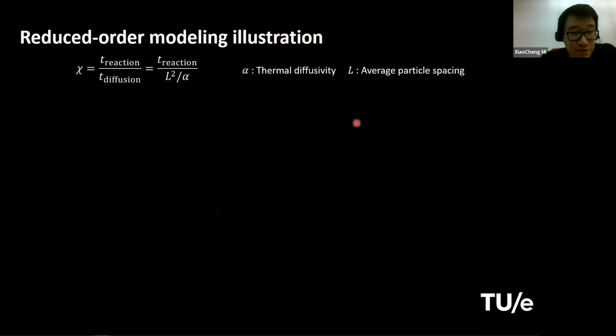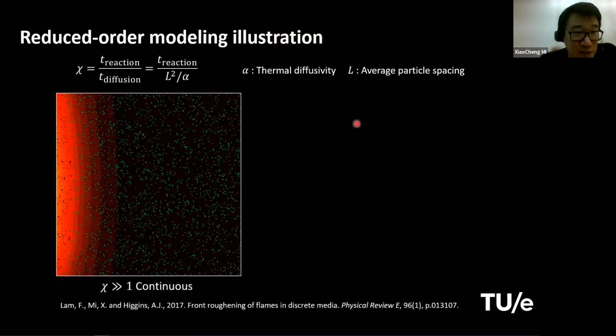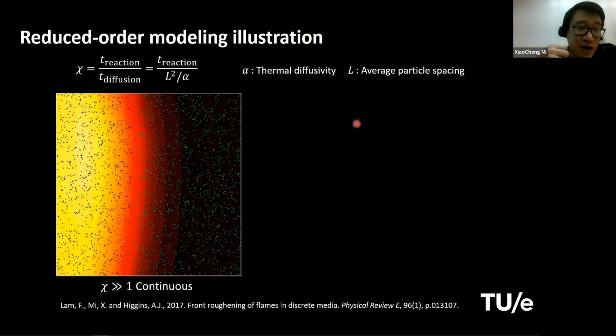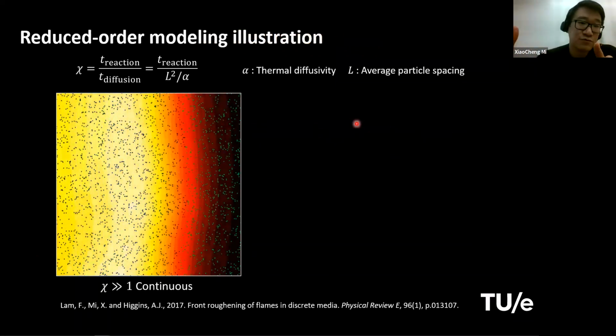And if this parameter is very large, much larger than 1, that means the reaction time is much longer than the interparticle diffusion time. Then after a particle releases energy, it has enough time for the heat to smear out and become smooth over the space. So the resulting flame structure using a toy model, it's not really an iron flame model. It's a very simplified theoretical model that we used to study this problem a few years ago. At this very large chi parameter regime, you see a flame that is continuous and very similar to what we have seen as a laminar flame in gaseous flames.